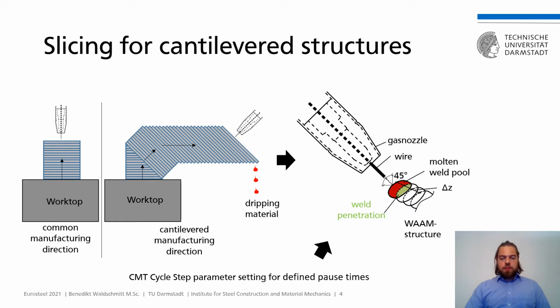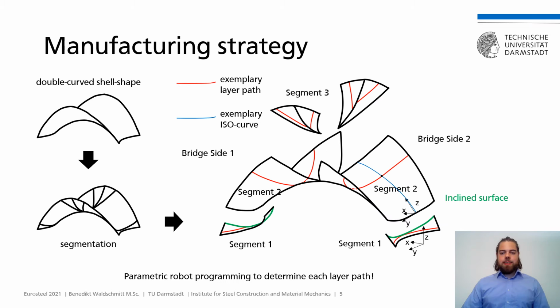While for conventional additive manufacturing processes, slicing can usually be generated using G-code, we had to come up with our own segmentation of layers. While the left-hand side shows the case of a common slicing and manufacturing direction, the right-hand side illustrates the layer construction for a cantilevered structure. The idea was to first tilt the application direction by 45 degrees to simplify the layer deposition and prevent material from dripping down. Besides, the CMT cycle step process was used, which allows a detailed controlling of the parameter setting to reduce the energy input. Precise information is given in our article. In addition, the welding torch orientation was changed 45 degrees to the horizontal to ensure an accurate hit in the center of the previous welding layer.